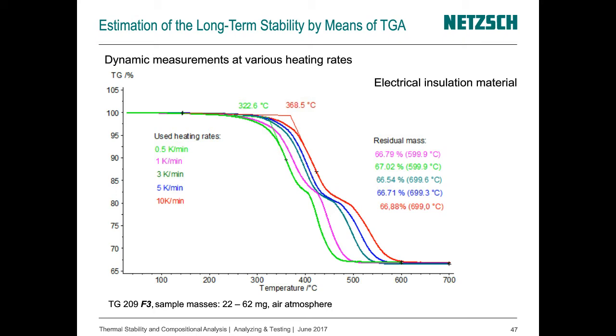Yes, of course, this is performed in the same instrument, because the CDTA signal is a calculated one, and it's calculated based on the sample temperature, which is measured by the sample thermocouple. And the sample thermocouple, for example, is part of the sample holder.